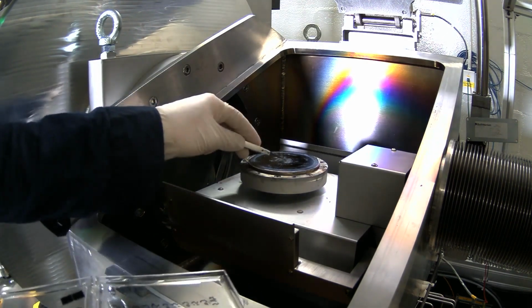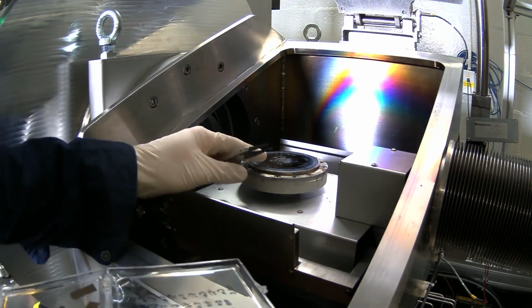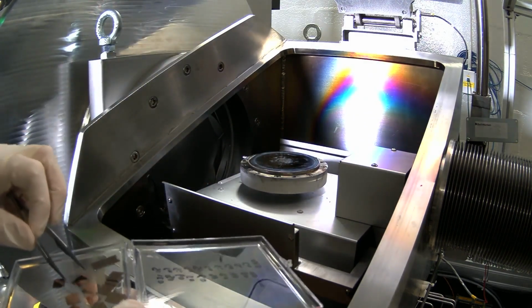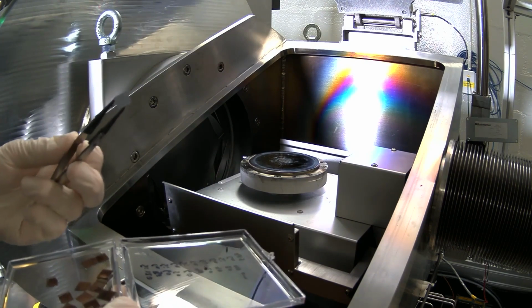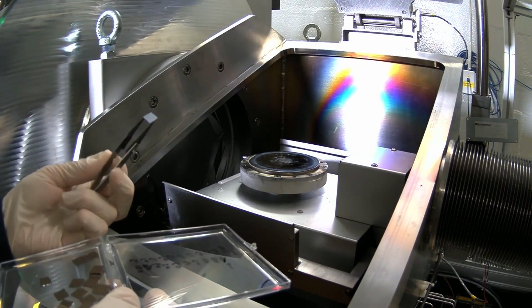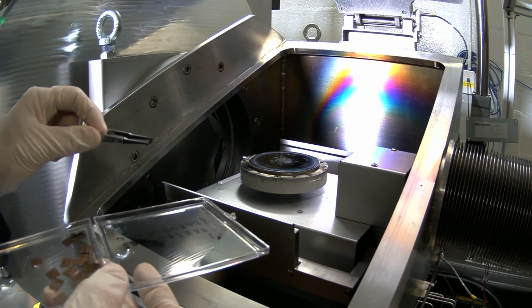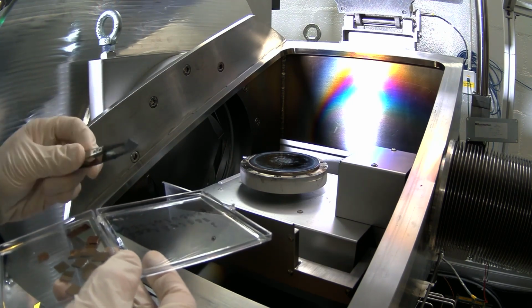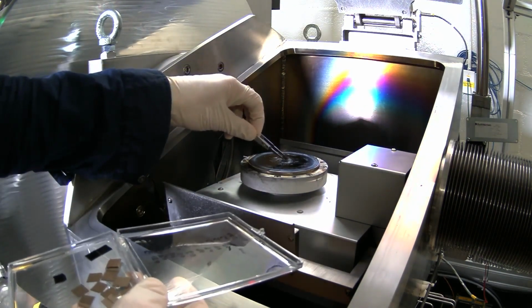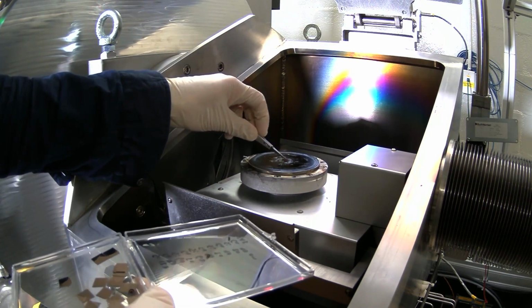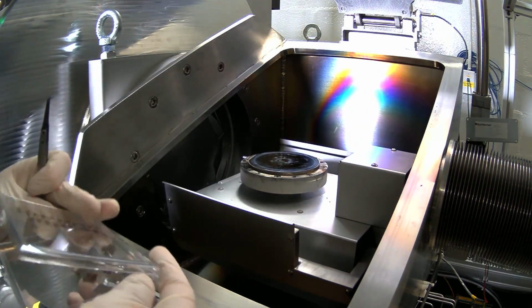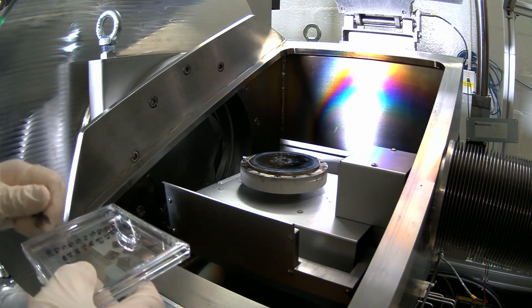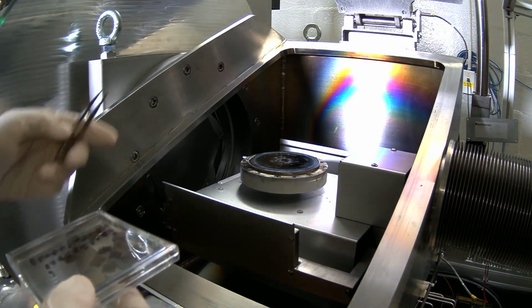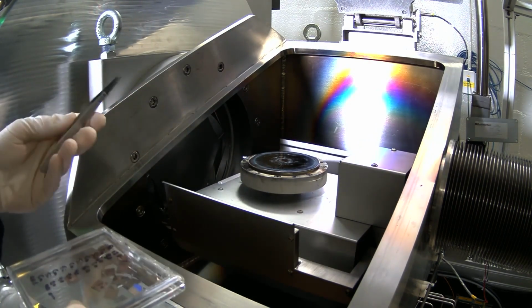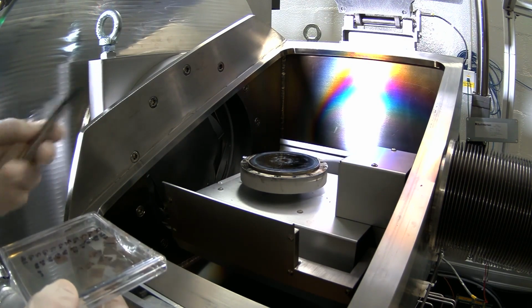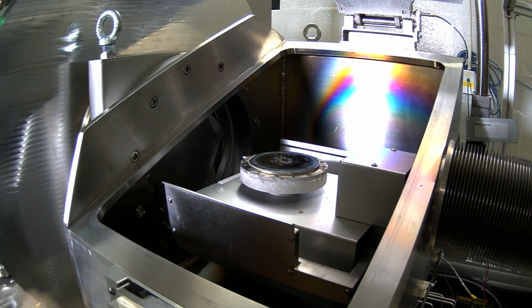Usually these stickies, I can use them several times and then I just scrape it off and put a new one down. So I have here a chip, a silicon wafer that was coated via magnetron sputtering with alternating layers of copper and silicon. The thicknesses of those layers depend on the layer: they're 20, 40, 60 nanometers thick. The point of this is that it simulates an M1, M2, M3 of an actual logic chip.